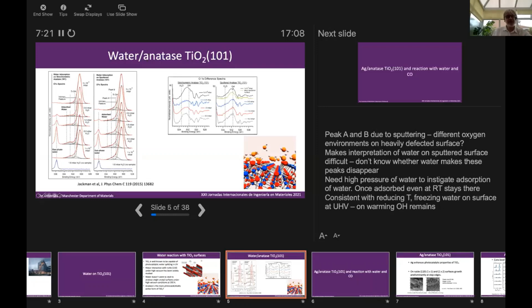On the etched surface, we see at the very lowest water exposure, 0.6 millibar, we don't really get much molecular water adsorbed. And we think that's because the reaction with the oxygen vacancies on the surface is so fast that they're very quickly mopped up. And again, the end result, when we pump everything away, is that we end up with some hydroxide present on the surface. Okay, an increase in hydroxide. So actually, it doesn't really matter very much with anatase whether you start with a stoichiometric surface or a surface rich in oxygen vacancies. The end result is you end up with a hydroxylated surface, but on the defect surface, the surface that's been etched, you find there is a little bit more intensity associated with these subsurface defects. So it looks like the defects actually transfer subsurface.